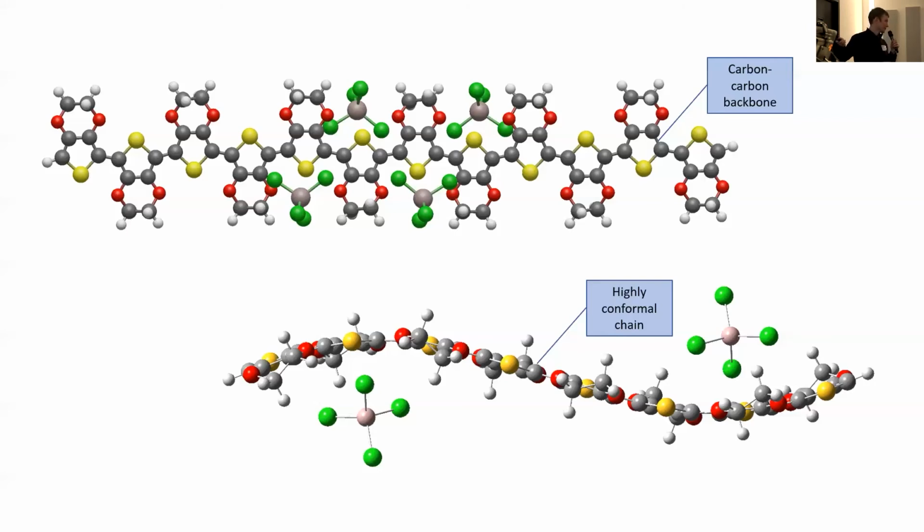It turns out the actual positions of the anions, the most dominant effect, and the minor deviations in geometry are not so important, which allows you to do this work without having to carry out thousands of calculations for every single arrangement of anions.